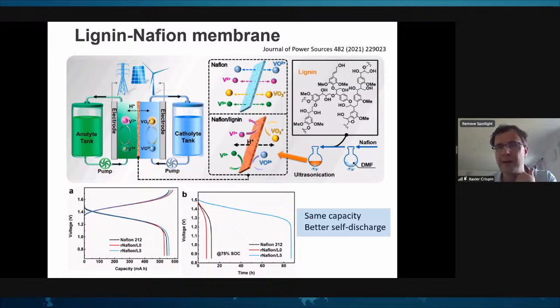This is what is called the self-discharge. So when you charge your battery and you don't do anything and you look at the open circuit voltage, how much the voltage is spontaneously decreasing. Here, if you don't have lignin, you see that within 10 hours, the potential drops significantly because all the ions are just crossing the Nafion membrane. But with the lignin coatings on top of that, you basically have a much longer self-discharge. You see, you get 90 hours. So it's a much bigger improvement.